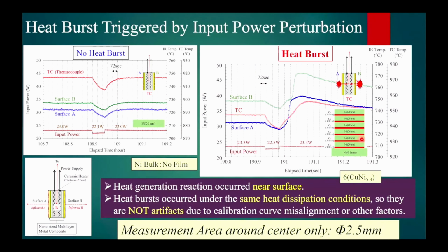But if we use this kind of multilayer thin film, input power goes down and accordingly surface temperature and thermocouple temperature go down, and return to the original value. After that, at this point, suddenly the surface temperature increased like this. It's a heat burst. And this heat transferred to the center, so the thermocouple temperature also increased like this. Of course, during this process, we did not add any extra energy, but we got the energy like this.